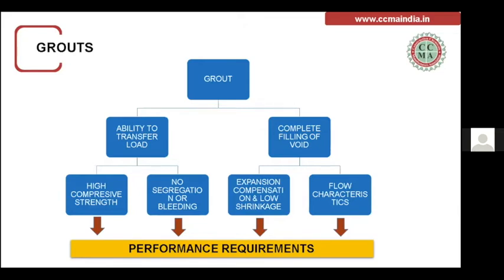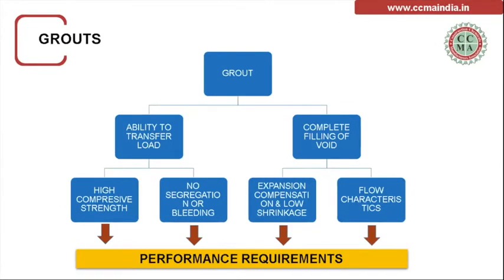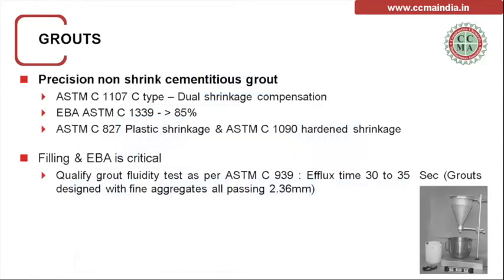Then what we design in the grout, as a manufacturer, by specifying, is high compressive strength. There should not be any segregation or bleeding while pouring the grouts. Then expansion compensation, and it should not have either hardened shrinkage or plastic shrinkage. That is C-type grouts, which specifiers select while picking the performance of the grouts. And the most important thing, apart from all these, is flow characteristics. This plays an important role to achieve complete void filling and an effective bearing area as per design greater than 85%. So this is the very basic structure of the grout performance requirements which users or specifiers will look at broadly to start with. This has been discussed in detail, as I told earlier.